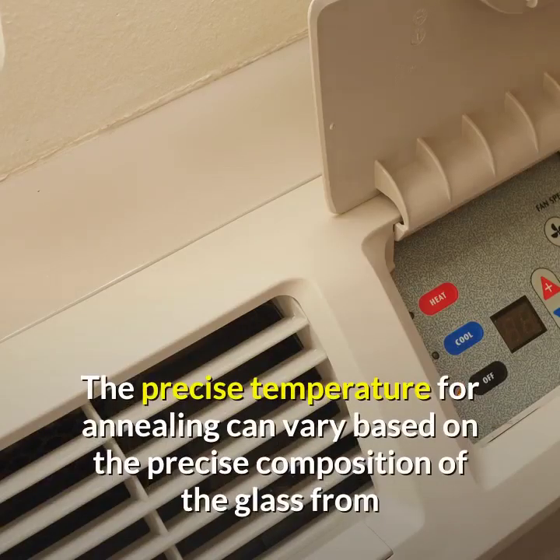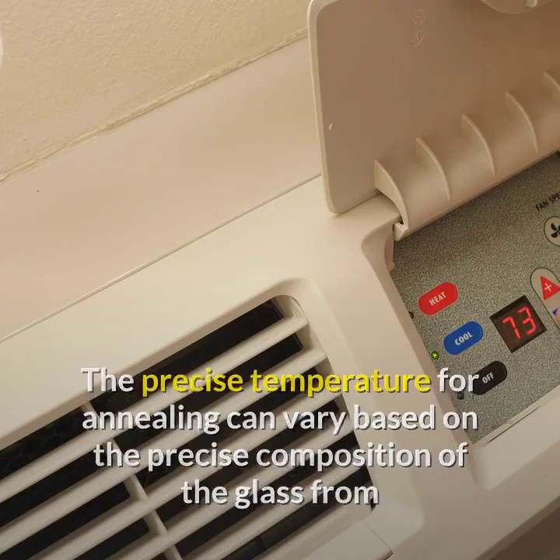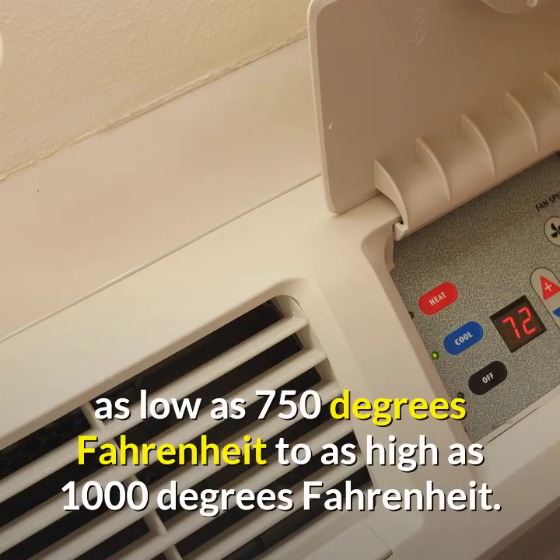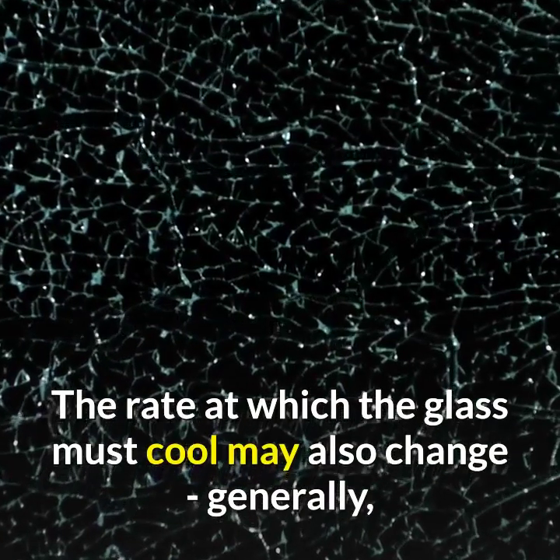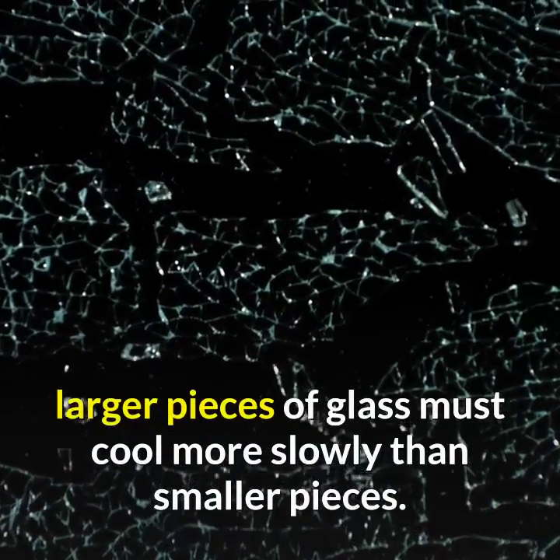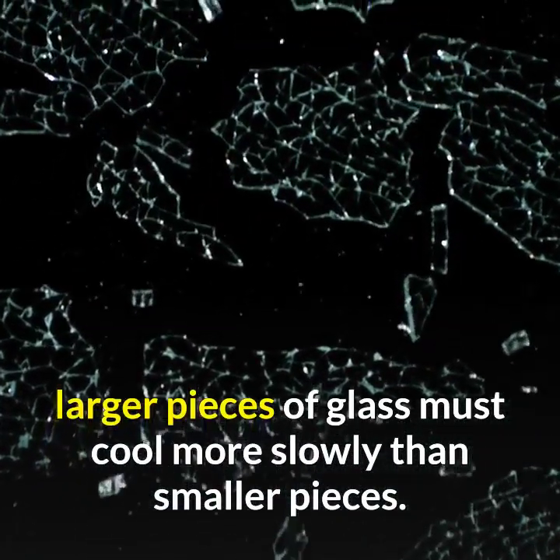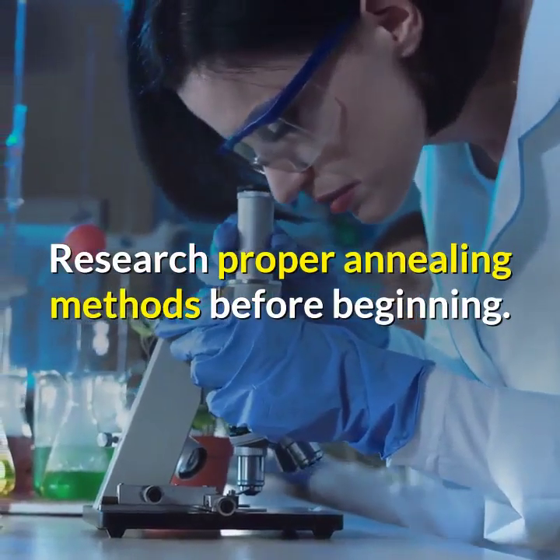The precise temperature for annealing can vary based on the precise composition of the glass, from as low as 750 degrees Fahrenheit to as high as 1000 degrees Fahrenheit. The rate at which the glass must cool may also change. Generally, larger pieces of glass must cool more slowly than smaller pieces. Research proper annealing methods before beginning.